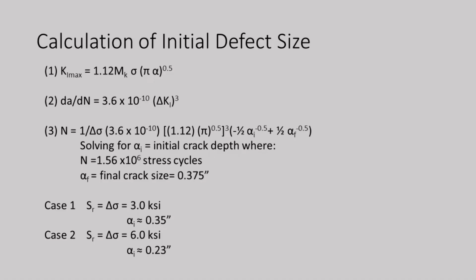And this particular number is relevant for the carbon steels. And you can take this K value and plug it in and do some integration and stuff, and you come up with this equation number 3, and we can plug in our live stress values, delta sigma. We can plug in then the final crack size, which we've measured, and then we know what our N is. It's this 1.5 million approximate stress cycles.